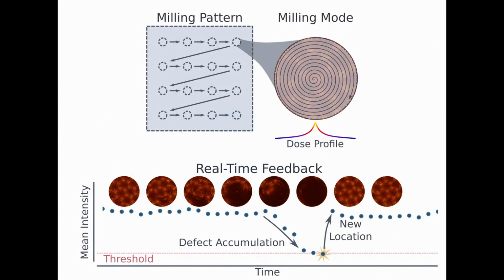We began by automating the milling of holes in graphene using an accelerating voltage of 100 kV, which is above the displacement threshold for carbon atoms in graphene. The automation enabled us to perform repeated experiments with the same experimental parameters to gather statistically meaningful datasets.